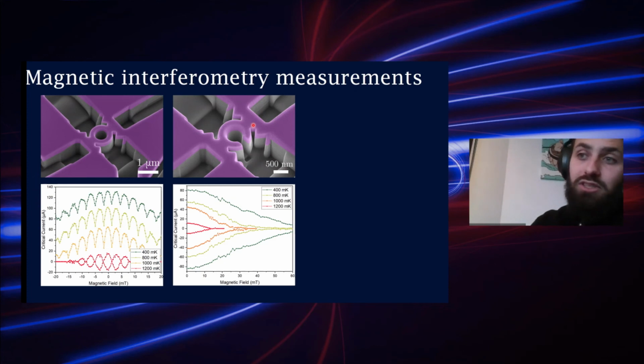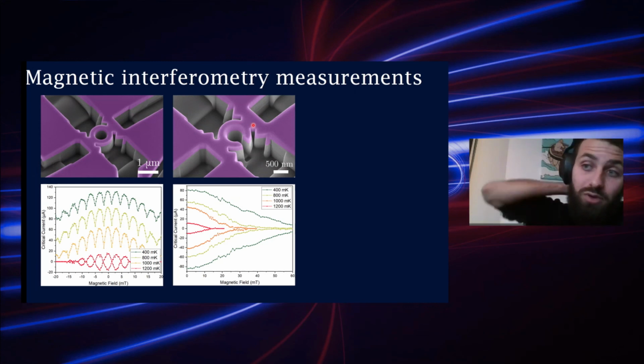While doing these measurements, we sweep IV characteristics, and for the lower temperatures the critical current is quite high, so if we swept the full polarity range it would take a lot of time. These measurements, per curve with a single polarity, take about 12 hours to make, so sweeping both polarities would increase that to 24 hours. So it's simply a time constraint. Whereas for the high temperatures, you can sweep from -30 to 30 microamps, since the critical current is so low.